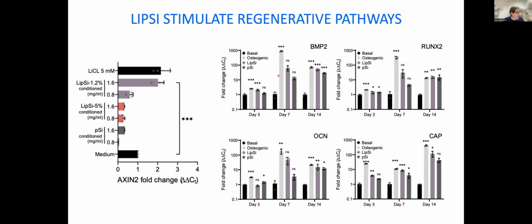And indeed, by introducing the lithium, we do stimulate the regenerative pathways that we want. So this is evidence of stimulating beta-catenin. Axin-2 is the first gene downstream of GSK3 inhibition. And we can see that when we use this particular type of lithiation, so 1.2% lithium, which has sort of an intermediate release, it has a 50% burst release, and then it sustains release over a couple of days.